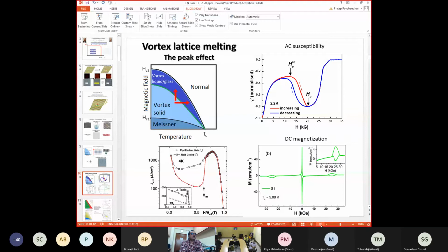You can also get the same thing by, instead of increasing magnetic field, increasing the temperature at a fixed magnetic field. This phenomenon, which is called the peak effect, and which is sort of the most telltale signature of the melting of the vortex lattice, can also be seen in other measurements, like for example AC susceptibility, where instead of a peak this manifests as a dip, because larger critical current means stronger diamagnetic response. So instead of the diamagnetic response monotonically going to zero from a negative value, you see this anomalous change. And this is a signature of this order-disorder transition. In magnetization, you can see this as opening up of the hysteresis loop and so on.